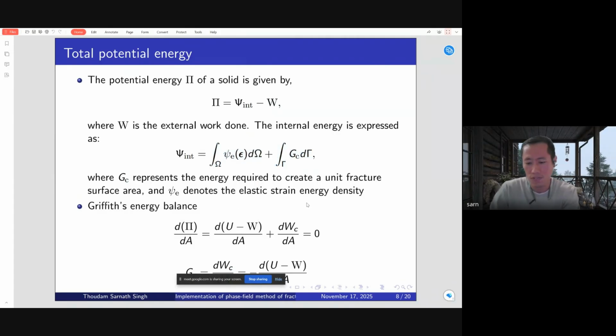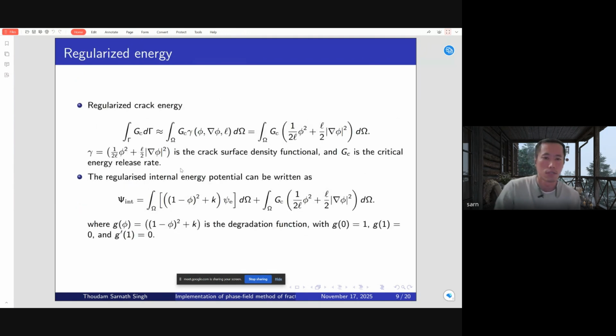So now let's use the smooth function. This is the total energy, while this is the total energy associated with the formation of the crack. And notice that this integral is a surface integral. Now, using the smooth function, you can write this expression in this form. Here the surface integral is changed to a volume integral, and this part is known as the crack surface density functional. The meaning of this is that they define the crack as a density. Crack is actually a surface area, but in this case we are defining the crack as a density.